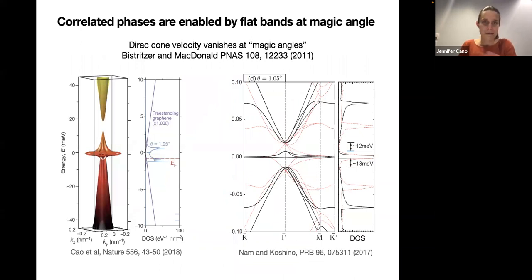To be a little bit more precise, you can do some numerical simulations of this. So this purple band is the density of states in a single layer of graphene. So that's just coming from the Dirac cone. And when the bilayer graphene is twisted at this special angle of 1 degree, then you see that the density of states changes dramatically to this blue curve. It's very sharply peaked near zero energy, which is corresponding to this flattish band here. And then it's basically zero for a little bit, which is corresponding to these little gaps on either side. So it's a dramatic change from a single layer of graphene.